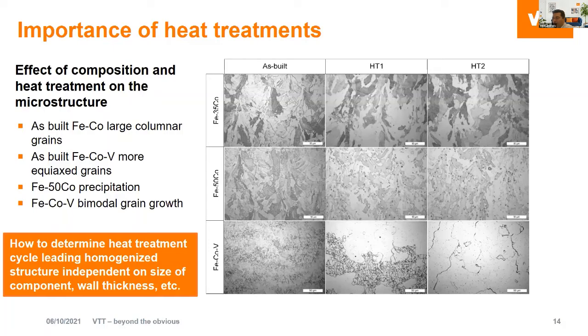And probably the most difficult thing in the optimization of this heat treatment cycle is how to homogenize that structure so that the achieved microstructure is independent of the size of the component and also the wall thickness of the component. So that we can say that every time you use this type of heat treatment for this material, you will get the same results out of your system.